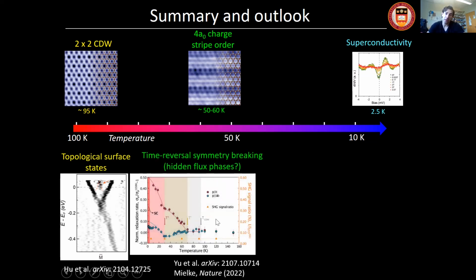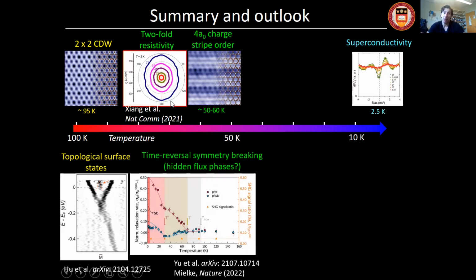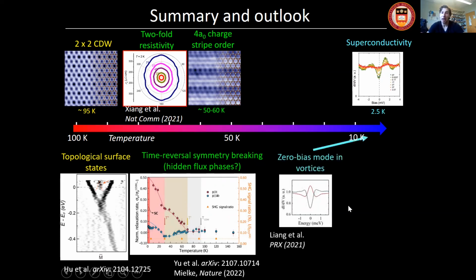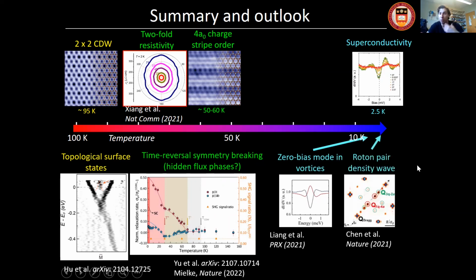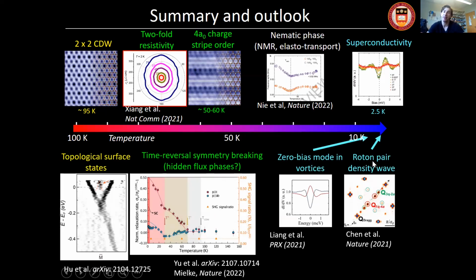MuSR found distinct temperature scales, and depending on which MuSR group you ask, they might be close to the charge density wave transition or somewhere below, possibly consistent with this 4a0 charge stripe order as well, which could be indicative of time reversal symmetry breaking. Resistivity measurements show twofold resistivity closer to low temperature, but maybe also extending all the way to the CDW transition, zero bias modes in vortices in the superconducting state, and an exotic pair density wave also in the superconducting state.